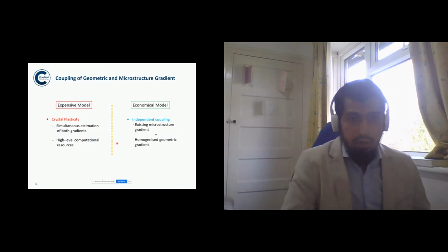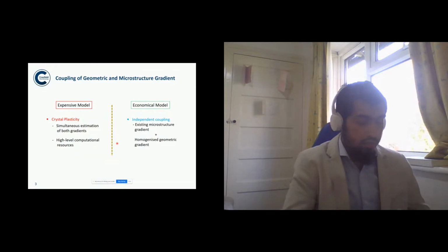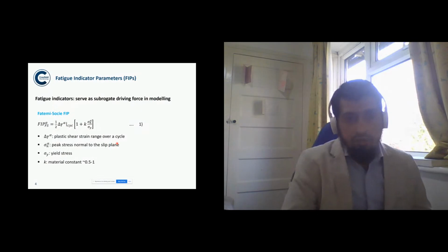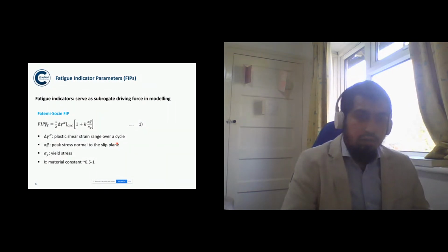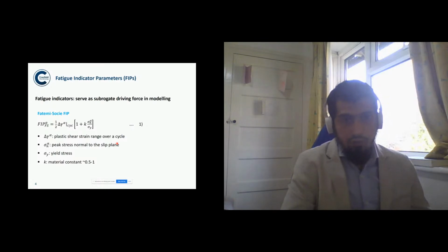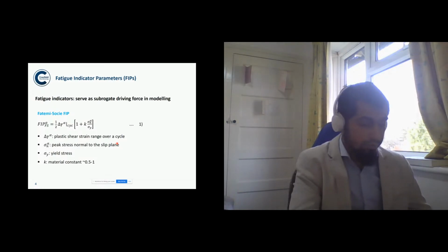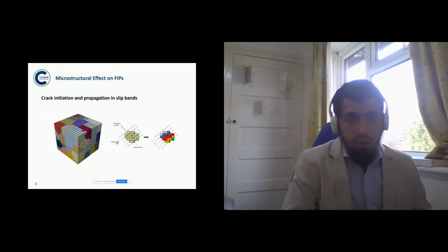Here I am going to explain the coupling of geometric and microstructure gradients through the expensive and the economical model and make a comparison. First of all, since I have mentioned small fatigue cracks are driven by the local shear, we have considered a fatigue indicator parameter based on the shear range proposed by Fatemi-Socie. It serves as the surrogate driving force in the modeling and can be used to study the effect of different geometric and microstructure gradients. So these are the driving forces in our modeling. First of all, we study the explicit effect of microstructure on the driving force, that is FIP.